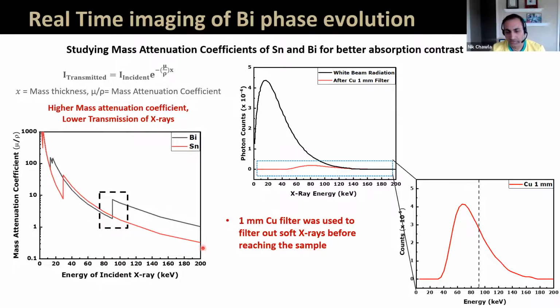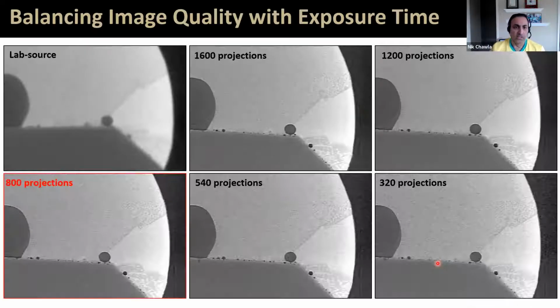And so we use a very nice software where you can put in the type of filter, the type of material the filter is, and the thickness, and you can predict what the outcoming photon count would be. And that's what this shows here. And we found out that for copper, we get very close to that 80 to 100 keV region. We're reducing the flux, but we're also narrowing down the energy range. So that worked out quite well.